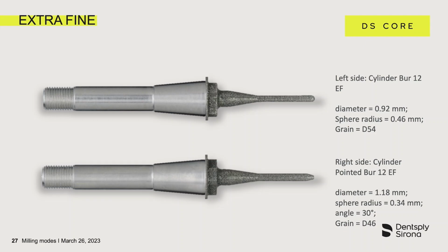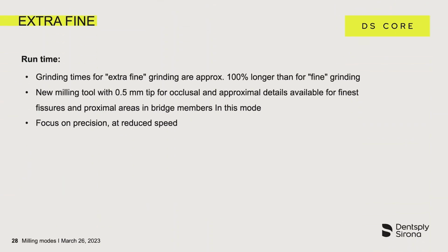Above, we see a cylinder drill 12EF. It has a diameter of 0.9 mm, a ball radius of 0.46 mm, and a grain size of D54. Below, we have a cylinder point drill 12EF, diameter 1.18 mm, ball radius 0.34 mm, with an angle of 30 degrees and a grain of D46. The grinding time for extra fine grinding is approximately twice as long as for fine grinding.